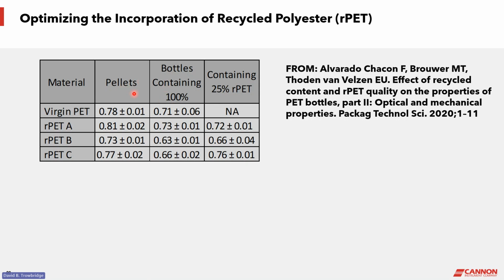And then they ran the pellets through their bottle forming process and saw a reduction in the intrinsic viscosity, which is expected. And then they did the same measurements for each of 3 particular recycled materials, saw the drop in the intrinsic viscosity. But what they were interested in was to see how the results of the intrinsic viscosity would be when they combine recycled PET with virgin PET. They did this in a 3-to-1 ratio and then measured the intrinsic viscosity after forming a bottle with that composition. And they looked at the intrinsic viscosity to compare it to the 100% bottle composition of virgin PET. And they're looking for a significance over the other recycled materials. And it points to sample C as being the best in retaining the intrinsic viscosity at a high level.